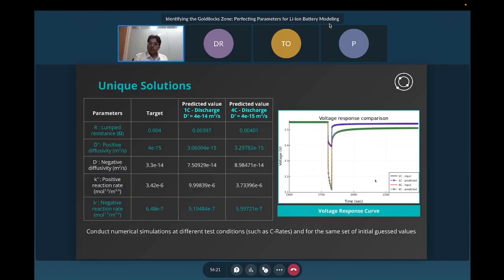Now, in order to ensure uniqueness, instead of just optimizing the parameters on single C-rate HPPC data, we created the HPPC data for 1C pulses as well as 4C pulses. And we did the optimizations on both of these cases by varying the initial guesses. And finally, we end up with a set of parameters that capture these voltage profiles.